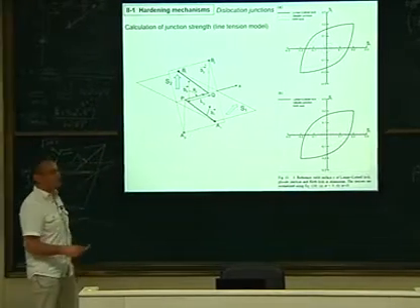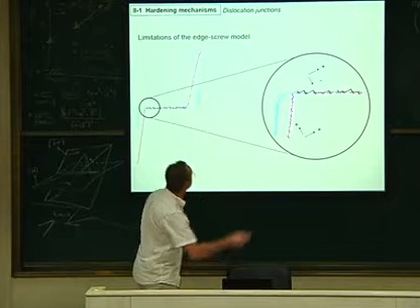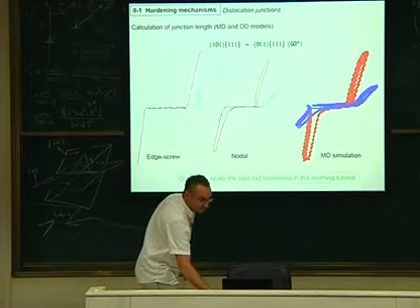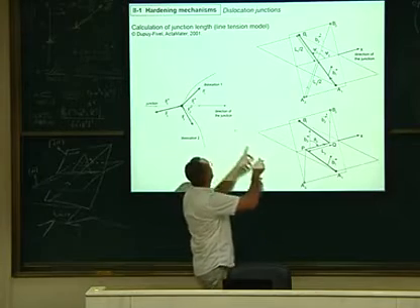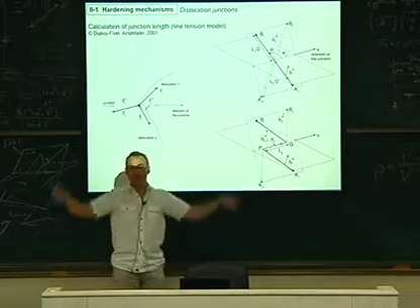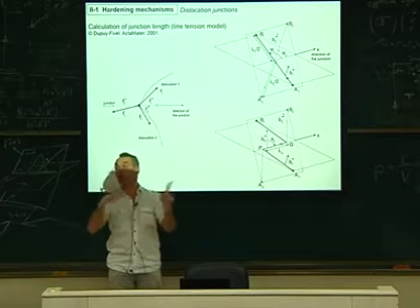Well, anyway, just imagine that, of course, out of this model we are able to visualize and compute the length of this dislocation junction versus the parameters that we put in the model. So with these angles, you change your angle, you measure the new length, you change the angle, you measure the new length, and that way you can have a description of all the possibilities for the dislocations to form a junction or not.